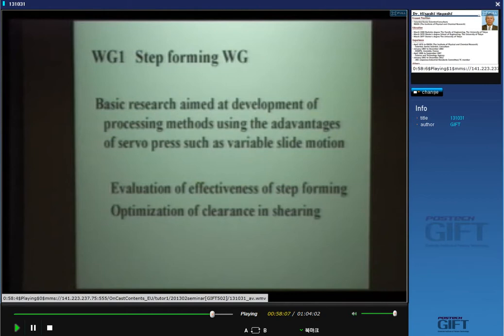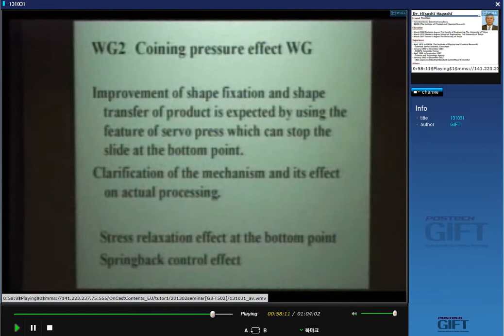And the second working group is the coining pressure effects. In this case, they want to improve shape fixation and shape transfer of products by using the feature of the servo-press, which can stop the slide at the bottom point. And also, they want to clarify the mechanism and its effect on actual processing. Through this experiment, they propose that the effect of stress relaxation at the bottom point should be taken into account. And of course, the coining pressure effect can be applied to spring back control, but this experiment has not been done.